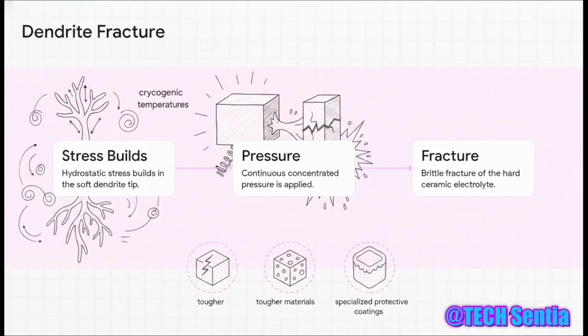By running their tests in a vacuum at cryogenic temperatures, researchers proved without a doubt that this failure happens via external mechanical stress, not from internal electron leakage like some folks had hypothesized. It happens in 3 steps. Step 1. Hydrostatic stress builds up directly in the tip of the growing soft dendrite. Step 2. That concentrated pressure pushes continuously against the ceramic. Step 3. The brittle fracture of the hard solid electrolyte occurs.